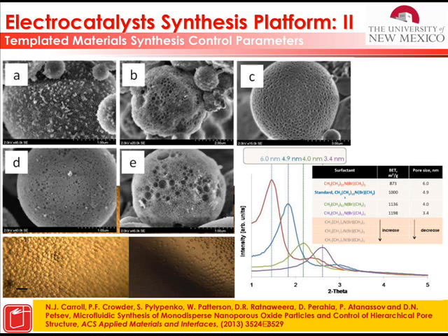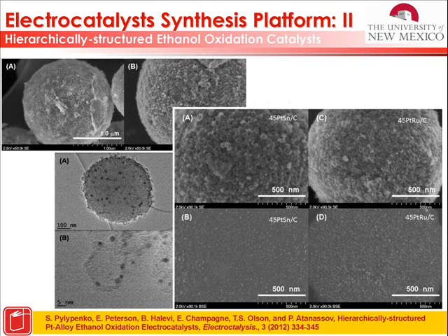So that is how you obtain these particles that have the catalyst phase deposited within the pores. Look at this image. It's like a negative image of the microemulsion directly. We recently published a paper discussing an ethanol oxidation catalyst based on the platinum-tin family that is exactly deployed within the structure of such a microemulsion. For liquid fuel cells, a hierarchical structure in a hydrophilic environment is extremely important because it is very easy to run your anode into a transport limitation mode.